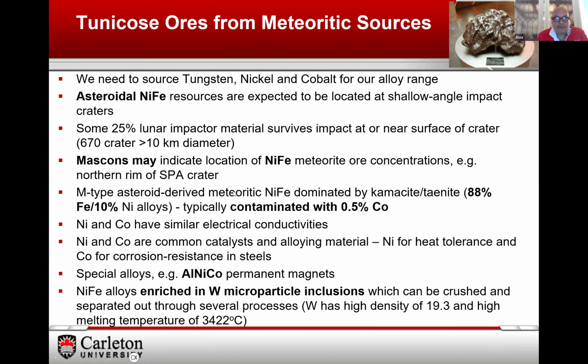The typical nickel iron material delivered by meteorites is dominated by kamacite or taenite. This is a variable mix of iron and nickel alloys, and they typically have about 0.5% contamination with cobalt, which is also a useful material. If we can access this material, we could start to build some special alloys, such as alnico, which is the basis of very, very strong permanent magnets.